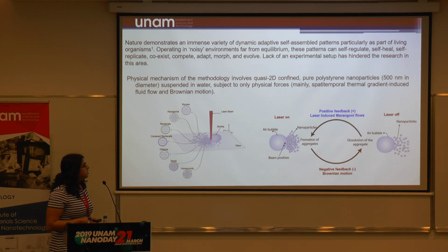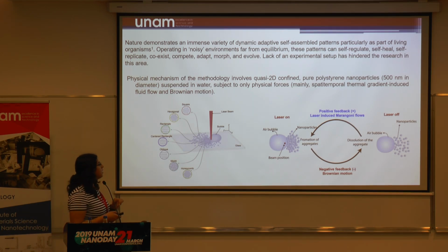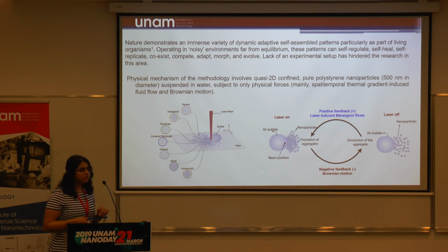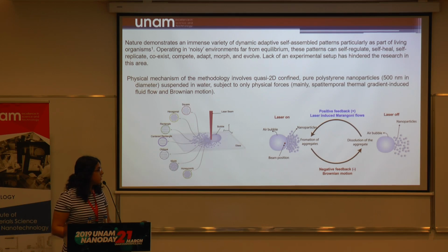Briefly, what we do is that we sandwich a solution between two optically transparent glass slides, and we shine femtosecond laser pulses to them here. And underneath the laser beam, there is a very hot spot, which will create a sharp temperature gradient and create Marangoni flows in the sample. Also, the liquid underneath the laser would boil and create air bubbles, which create boundary conditions.